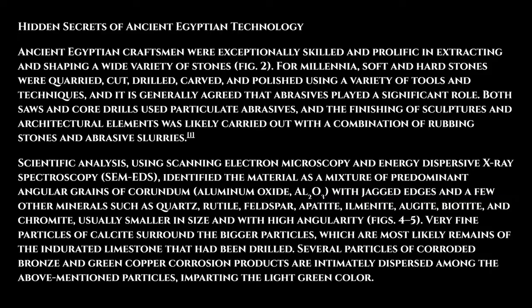Very fine particles of calcite surround the bigger particles, which are most likely the remains of the indurated limestone that has been drilled. Several particles of corroded bronze and green copper corrosion products are intimately dispersed among the above-mentioned particles, imparting the light green color. So those of you who continue to follow and support the narrative associated with lost ancient high technology are intentionally ignoring the legitimate science that has been conducted in this field. And it is very easy to do a small amount of research to dispel these type of myths.